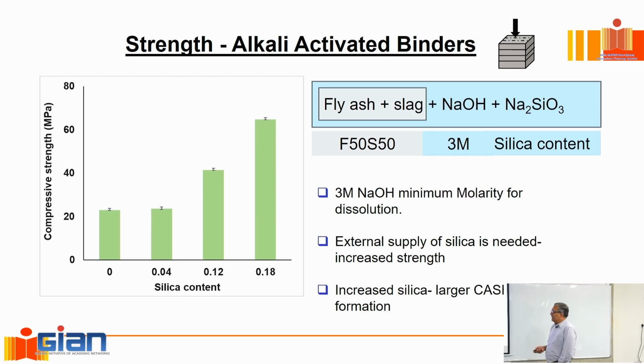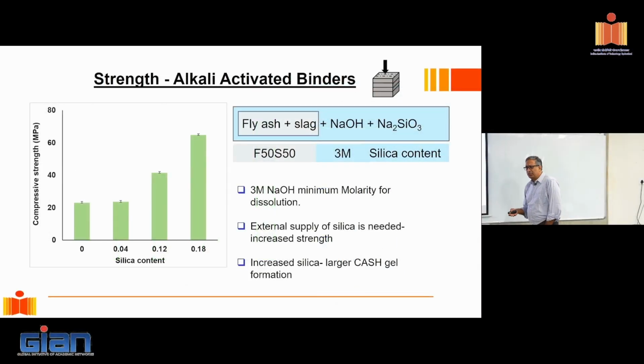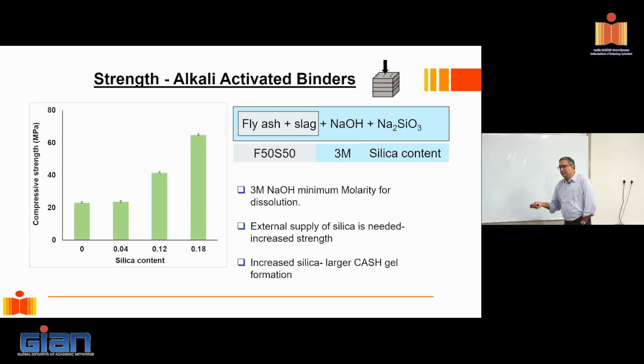Right? If I increase the silica content, typically my strength starts shooting up because I'm basically bringing in more silica that helps formation of either C-A-S-H or N-A-S-H, and that leads to strength improvement. So having silica in the solution is almost a must if you really want a good strength from the material. Only in rare cases where we are dealing with only slag, sometimes we drop sodium silicate. Otherwise, almost always you'll have to have that. And when you do that, then this proportion of these two matters, how much water I add, that controls the molarity, and the percentage weight of this to these two is another variable that I have to worry about.